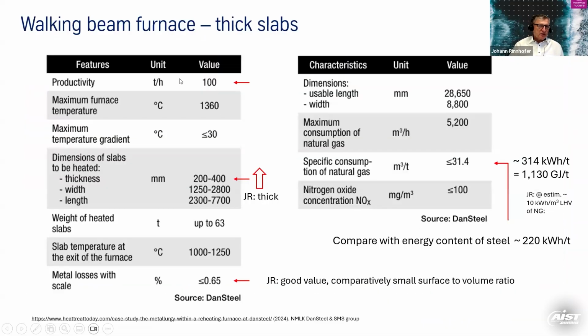Just a few data of this furnace. It has 100 tons per hour. It has 200 to 400 millimeter thick slabs. So it's fairly thick slabs. No, it's a heavy plate mill. You have only 0.65% metal loss. That means scaling, which is a very, very good value. You wouldn't have that with billets, most likely, because here you have a very small surface to volume ratio with these slabs. As I said, you can have 3%, you can have also more than that when you look at rotary hearth furnaces and small sized stock.